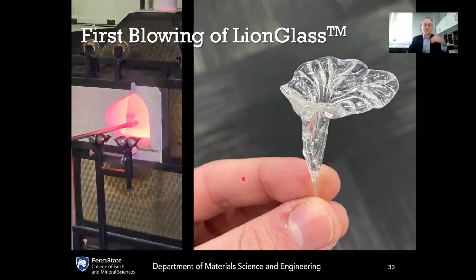So to be able to melt it and to form it properly, Arun was able to show that he could reheat it multiple times, and we don't have crystallization, we don't have phase separation. He was able to control the viscous flow behavior. He just needed to readjust, or recalibrate himself, because the temperatures are so much lower that it's not glowing nearly as much as soda lime silicate.